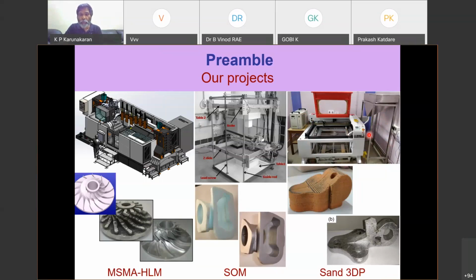Almost 1 order of magnitude less compared to the traditional laser. Traditional lasers are high frequency or radio frequency lasers. So they will have very quick on off of the beam. So we use a glass tube laser. It has a very sluggish response for on off, but that doesn't matter to us because typically in 3D printing, after every contour, people switch off the beam and then go to the next contour. In our system, we don't switch off the beam.